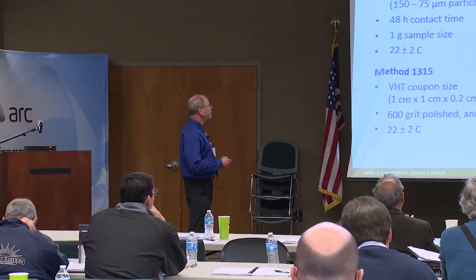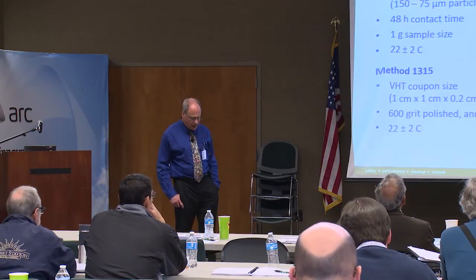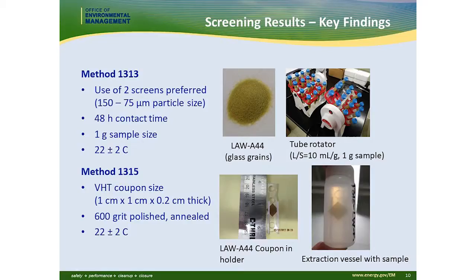Well, one of the important modifications for method 1313 was dealing with the particle size. The test method itself currently specifies the particles to be less than a threshold of 300 microns, and in turn does not have a greater than threshold. What we found was for reproducibility, it was preferred to use two screens, that being that the ground glass was less than 150 microns and greater than 75 microns in particle size. And you can see a picture here of the glass after it's been prepared.